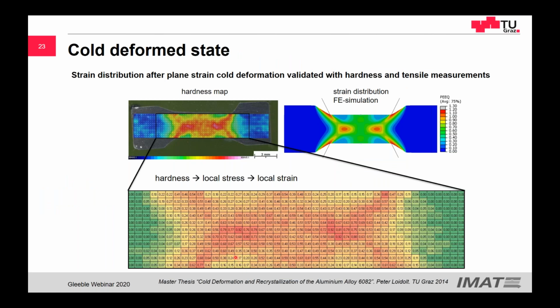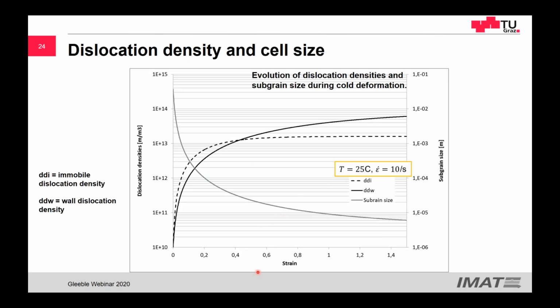I just come back one step again. So these are the local strain here with the local stresses that we implemented with our model in finite element simulations. And with this, we could estimate with the model the subgrain size as a function of the local strain, as well as the dislocation density, since our model is based on dislocation density.